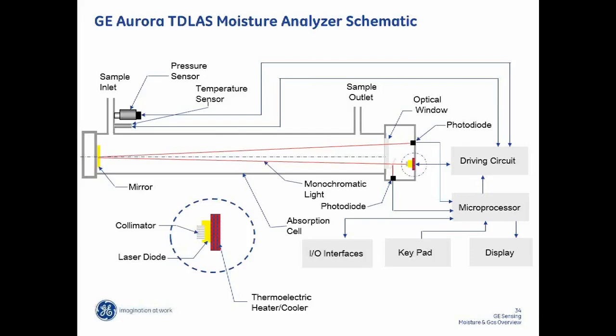So as the laser is tuned or ramped through a narrow band frequency in the infrared, there's a particular frequency where water absorbs the energy. The water molecule has a unique vibrational and rotational characteristic that absorbs that photonic energy. So you're getting, at that particular frequency, less photons than what you put into the system. And the longer the path length, the more absorption or loss of signal you'll get if there's water in it. So by having a constant length, we're able to look at the absorption characteristic and determine that, yes, there's water in there, but not only that, how much water, by looking at the loss of signal or the absorption.